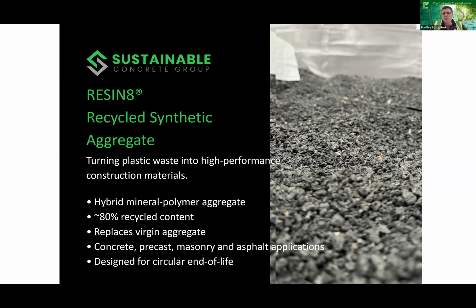So we're cutting off the pathways to microplastics and to leachate, which means that when this aggregate is used in the concrete, down the track, at the end of life when you're recycling aggregate or your asphalt, this is a clean aggregate. From that point forward, once it's in the cementitious matrix or the asphalt matrix, it's basically infinitely recyclable as an aggregate. So it can continually be recycled that way. It's a full circular product, which is why I was very excited to get my hands on it.